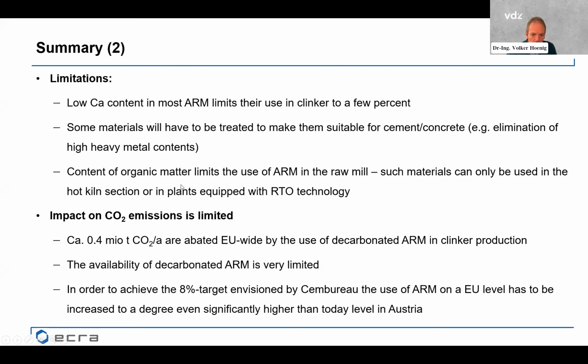The content of organic matter limits the use of ARM in the raw mill. Such materials can only be used in the hot kiln section or in plants equipped with RTO technology. And last but not least, the impact on CO2 emissions is limited. Today we have about 0.4 million tons of CO2 per year which are abated by these, but the availability of these materials is rather limited. So as I mentioned already, achieving this 8% target from the CEMBUREAU roadmap by this means is really challenging.